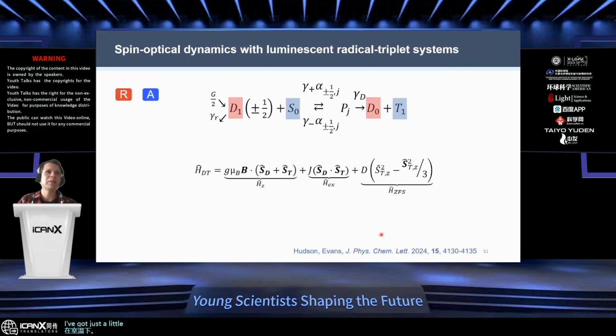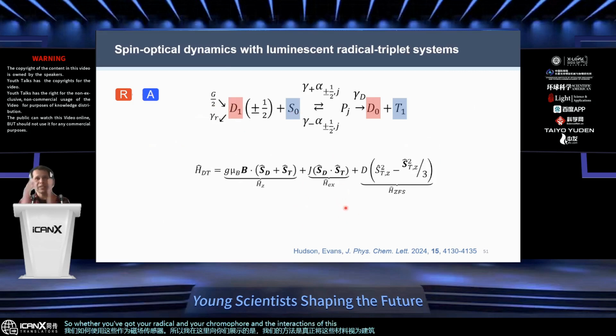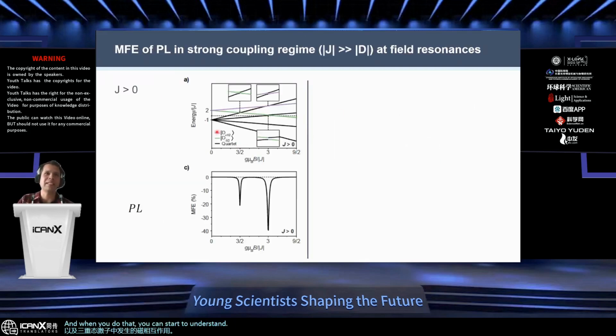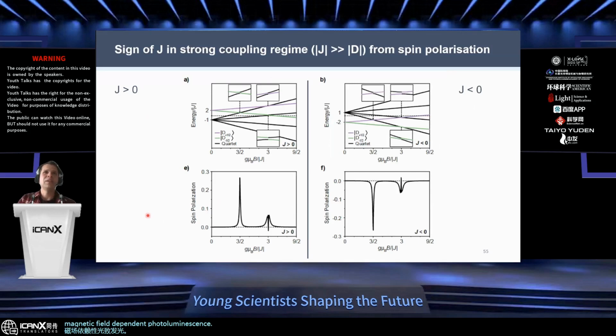I've got just a little bit of time, so I just wanted to tell you finally some of the work that was recently published last week, as we're now trying to dig into the opportunities to use these systems as quantum objects, and we're studying how we can use these as magnetic field sensors. Our approach is really to think of these materials as building blocks. You've got your radical and your chromophore, and the interactions of the system are the electron exchange interaction between your radical and your triplet state, and also magnetic interactions that happen within your triplet exciton. Now, when you do that, you can start to understand how magnetic fields lead to crossing points between these levels, which you can study through magnetic field-dependent photoluminescence. And we can also look at how we can change the spin polarization state of our system.